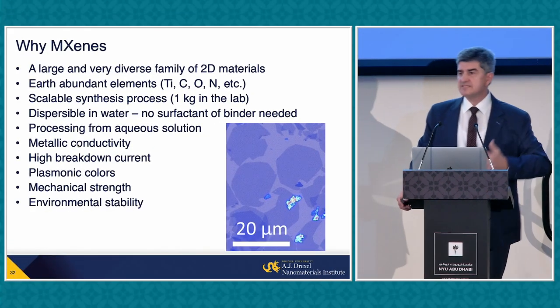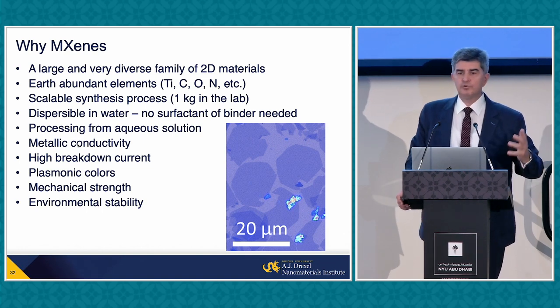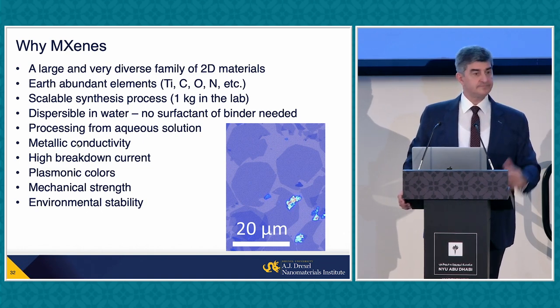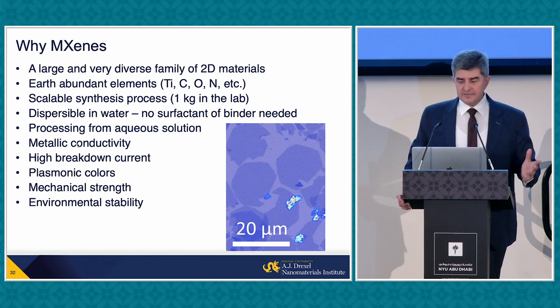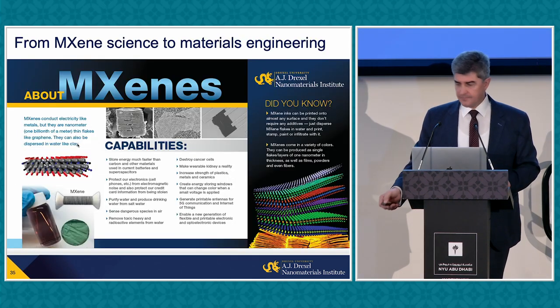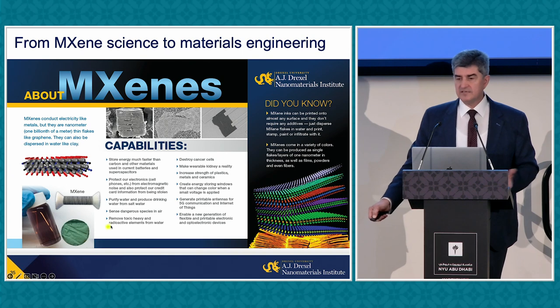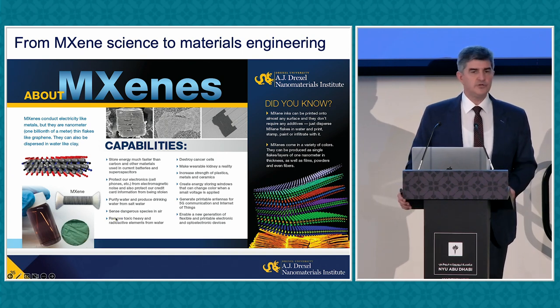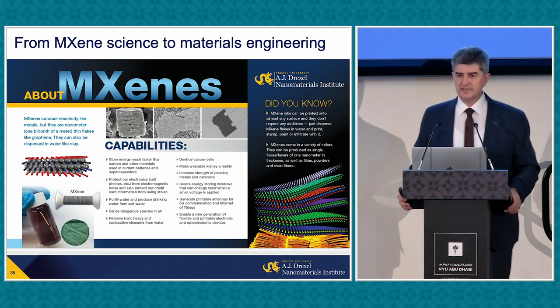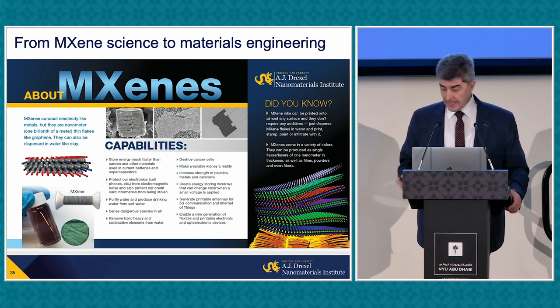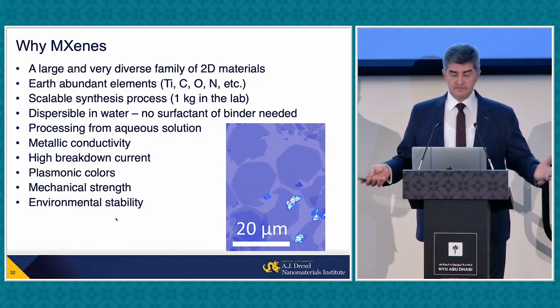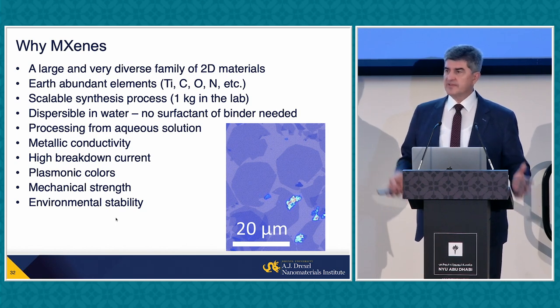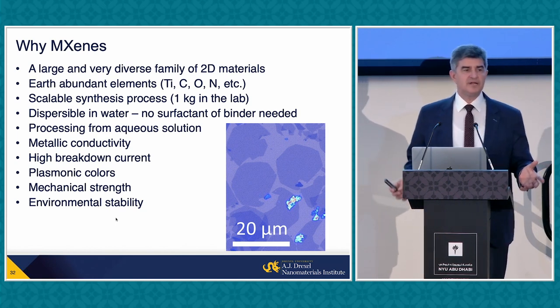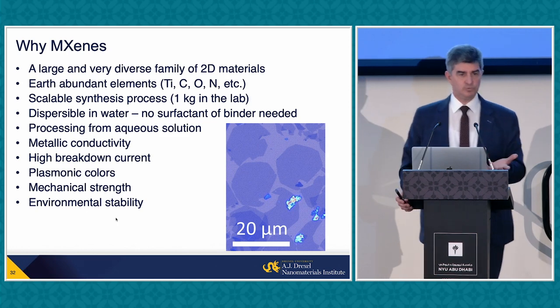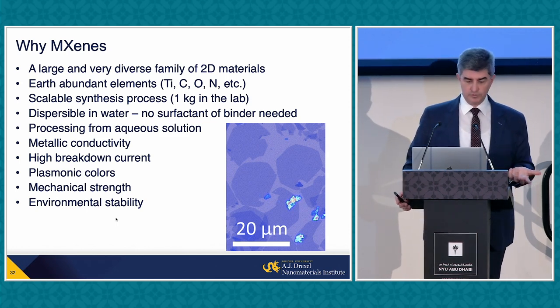And in addition, there are many other useful properties. For example, it has breakdown current two orders of magnitude higher than copper, similar to graphene. In bulk, in a film like the one you see here, it is an order of magnitude more conducting than reduced graphene oxide, which is used to make thicker layers in films. It has very high mechanical strength. Carbides like titanium carbide, tungsten carbide are used for machining metals, making cutting tools. They're very hard, very strong, high modulus materials.